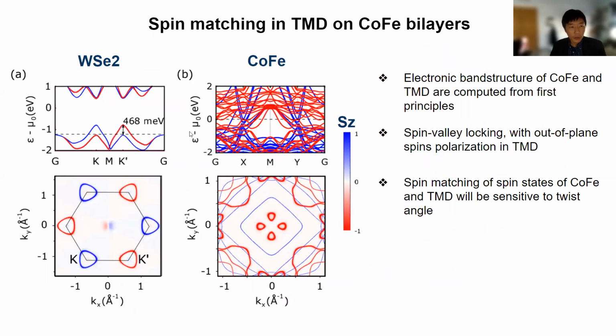Okay, so in order to study the injection of the spin into the cobalt iron, the first thing we need to do is to look at the band structure. And what I have here is the band structure of this TMD and the band structure of the cobalt iron. In the calculation, the equilibrium Fermi level is somewhere around here, which is very close to the valence band edge. And the blue and the red color denote the up spin and the down spin polarization. So you can see that the two valleys have opposite spin.